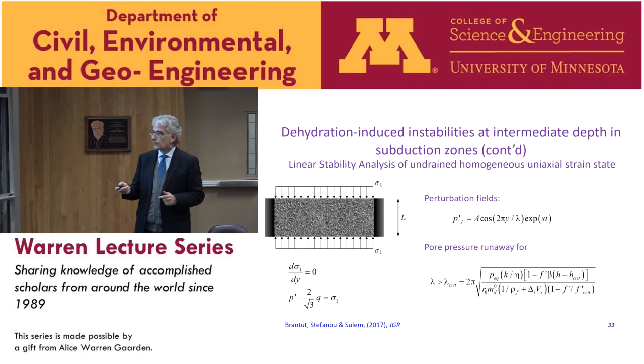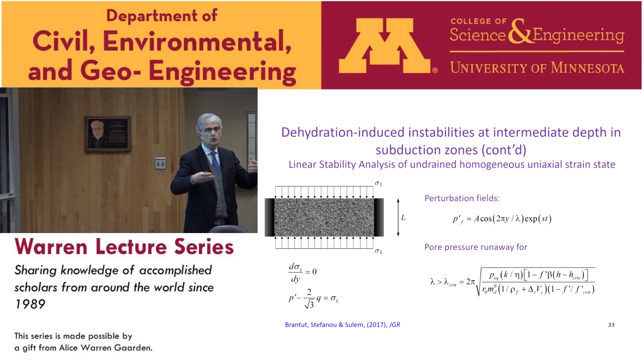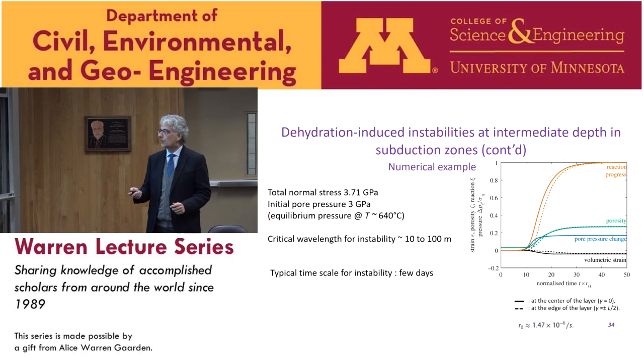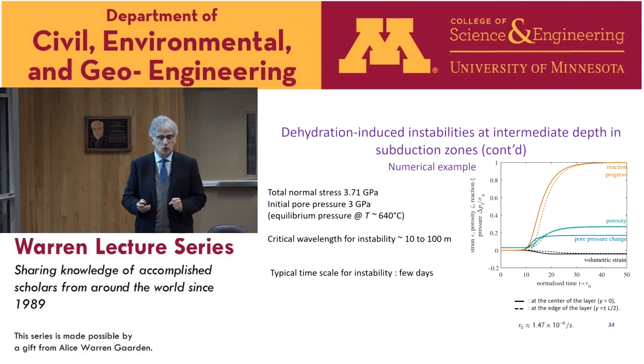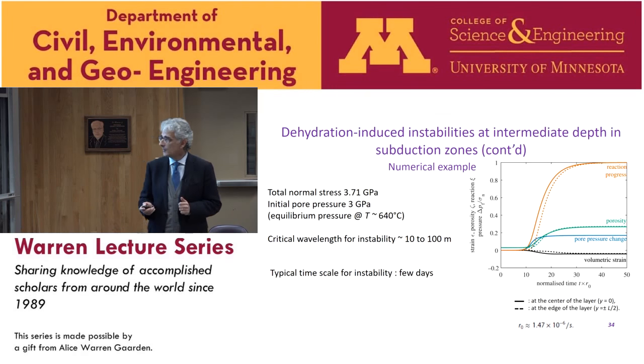Again, from the linear stability analysis, we have just the onset of the instability, but if we want to follow the evolution, we have to solve completely the problem. This is the 1D problem, and this is what we have done. These are the initial conditions corresponding to a fault, to a subduction zone at about 100 kilometer depth. The critical wavelength of the instability is a few tens of meters, and the typical time scale we find is a few days. So this is compatible with the observation of silent earthquakes.